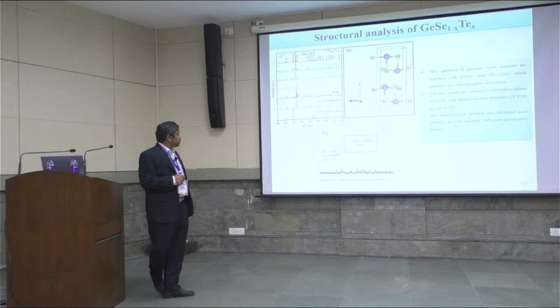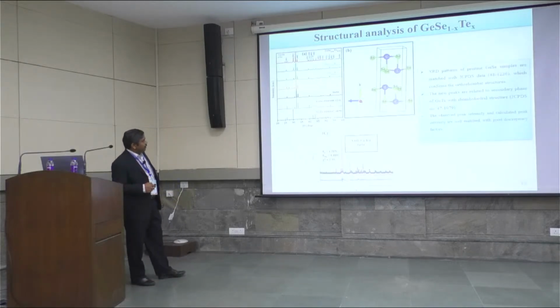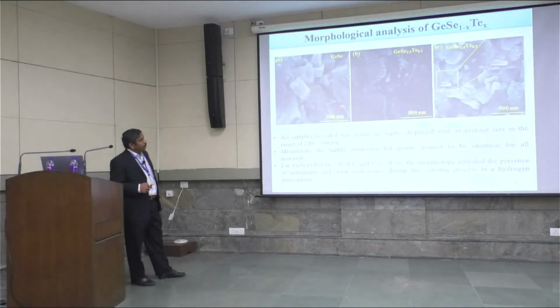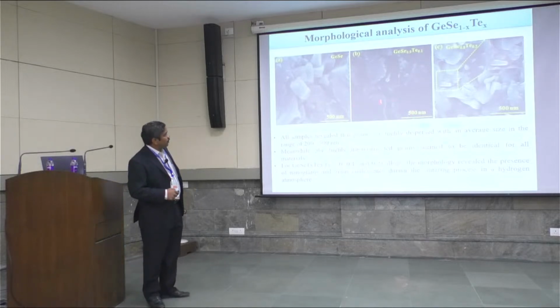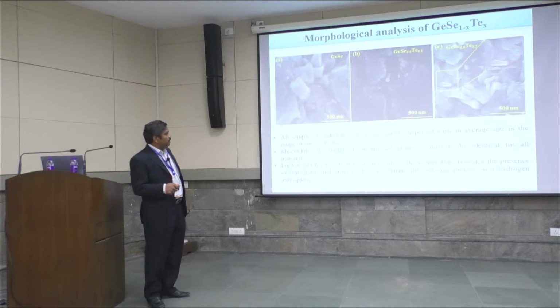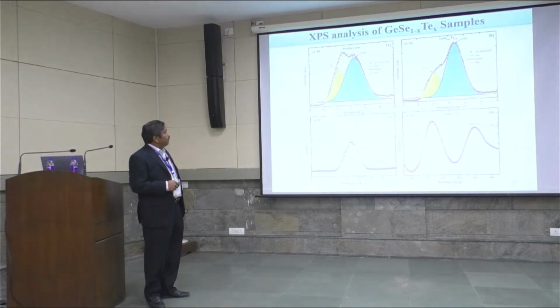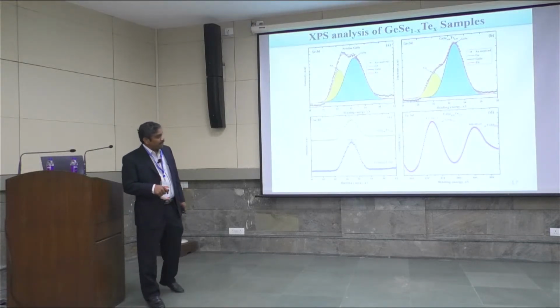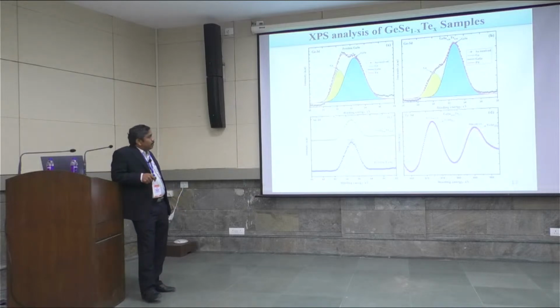And look at these structural features: the tellurium is completely substituted at the selenium site up to 10% of tellurium. And when the tellurium content is more than 10%, secondary phase formation of germanium telluride was observed. So structural variations are observed as a function of tellurium substitution in the germanium selenide. And the morphological features tell about the nanostructuring of the samples, and the grains are highly interconnected. And these interconnected grains help facilitate electron transport in these kinds of systems. The tellurium incorporation in the systems is confirmed using EDX analysis, that tellurium is completely substituted in the systems, and the binding states of the rest of the elements are confirmed.